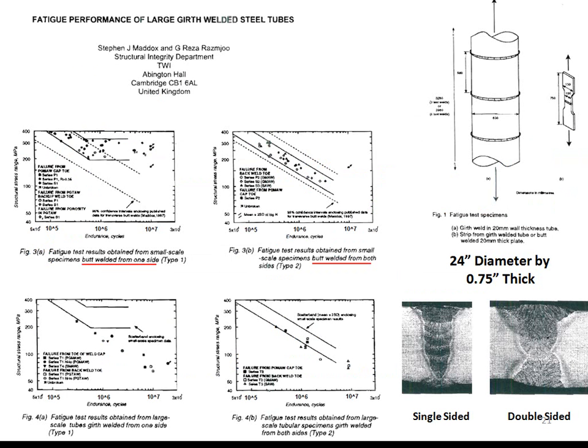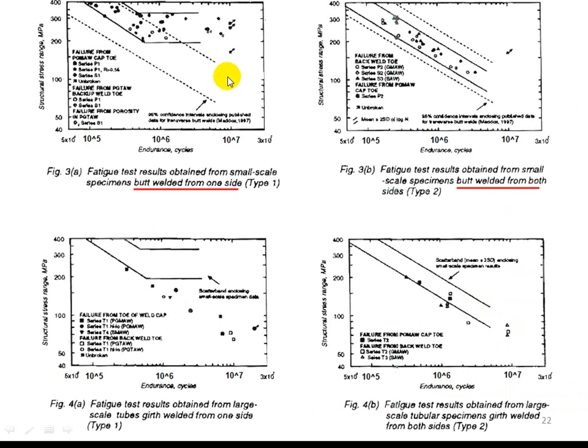From the fatigue performance of large girth welded steel tubes by Maddox, additional failure points can be taken and put on those curves. Here's a single-sided and the double-sided welds that they tested. These were for 24-inch diameter by 3/4-inch thick pipes. These are larger pictures of the plots from the previous page. Note that some welds show an endurance limit, and some welds don't. The Maddox tests suggest that larger specimens, real pipe, don't show endurance limits.